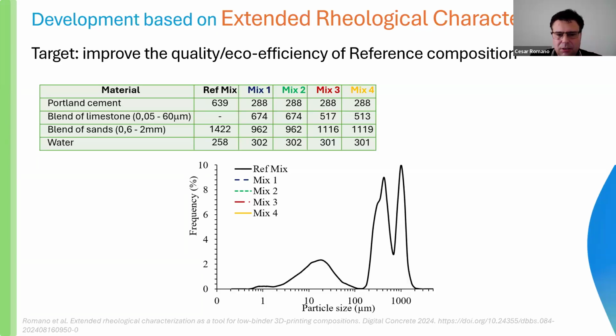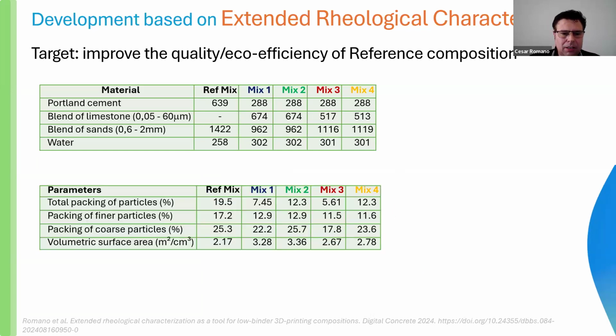So I'm showing here 4 mixes, but we studied a lot of mixes, and I'm showing just 4 for the example that I intend to show to you. We did this by replacing part of the Portland cement with a blend of limestone filler. So, changing the blend of sands and the blend of finer particles, we had these changes in the particle size distribution. And as a consequence of that, we had changes in the total packing of particles, the packing of finer particles, the packing of sands.